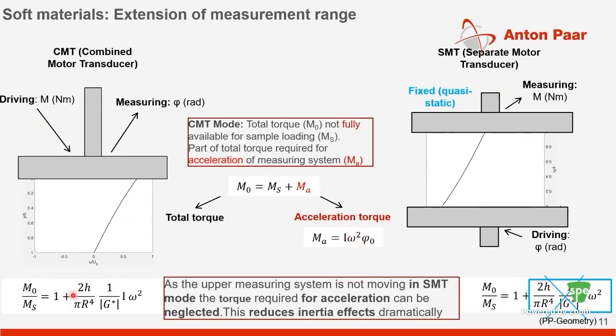That's why, if you do some simple quick math and take a ratio of the total torque to the sample torque in the CMT mode, it scales as omega squared. This is what you see at really, really high frequency—that spurious increase where your data is now affected by instrument inertia.